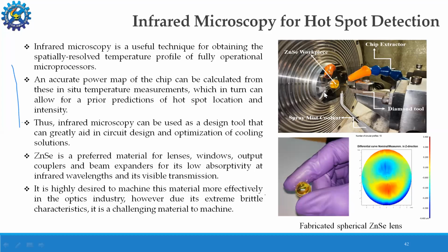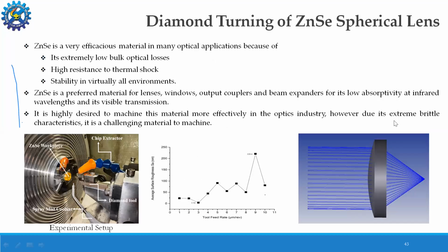So the challenge here was that we did the machining of zinc selenide material. It is a very preferred material because it can be used in the entire IR range, and also because of its special properties, like extremely low bulk optical losses, high resistance to thermal shock, and stability in all environments. So we designed as well as developed a plano-convex lens which could be used for infrared microscopy for the detection of the hot spot.